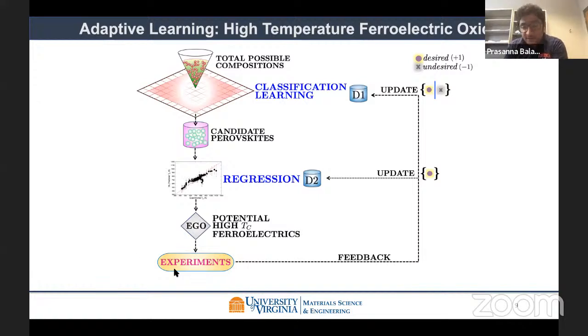And then we perform experiments. There are two levels of feedback. One is at the structure level. Our colleagues were able to process this composition through the powder metallurgy route and characterize the structure using X-ray diffraction. If the X-ray diffraction agreed with the prediction, then that's an interim success. After that, the colleagues were also able to measure the Curie temperature using dielectric measurements.